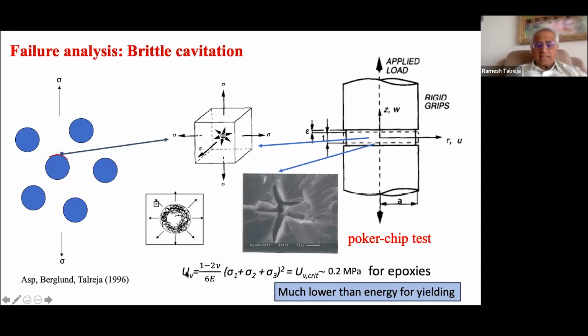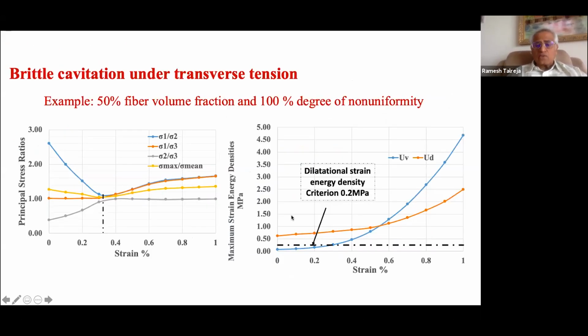The value of the dilatation energy density formula is here, and the value comes out to be for epoxy very small, 0.2 megapascal. What this means is there's no other mechanism able to compete with this particular mechanism. It's an energy dissipating mechanism, failure mechanism, and there's no other mechanism of crack formation that comes close to that. So this is sort of the first mechanism if its conditions are right. That is, it has dilatation energy density. Now, this is going to take time to describe, so I'll refer you to the paper.